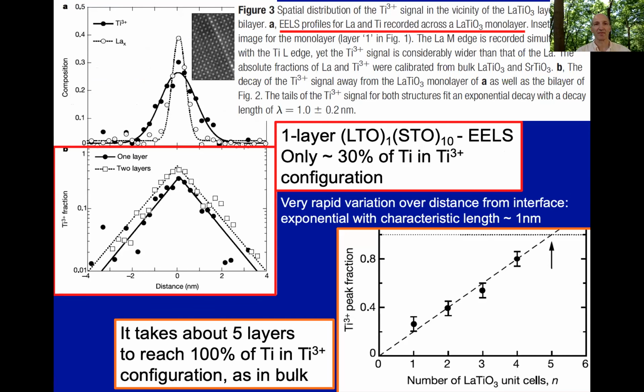And in fact, this can be documented. These are results obtained using electron energy loss spectroscopy from that paper, in which the fraction of titanium 3+ here in the bottom right is monitored as a function of the number of layers of the LTO sandwich. And you see that when there is a single layer of LTO, like in the previous picture, there is only about a third of the titaniums which are titanium 3+. So the system is significantly doped. It's a mixture of titanium 3+ and 4+, and hence it's expected indeed to be metallic.